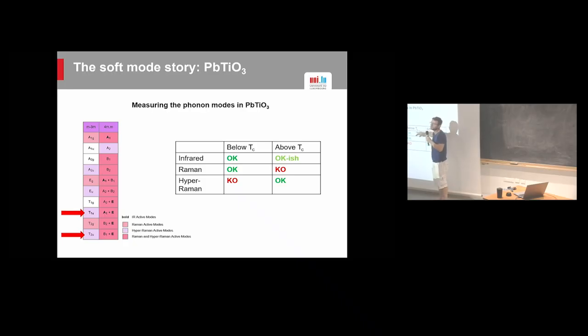Below TC, infrared is perfectly fine. Raman works too, because like I said, in ferroelectrics very often they are active in both. Hyper-Raman doesn't. It's not for symmetry reasons, but it's just that as soon as it's ferroelectric, you're blind because you have so much second harmonic generation that you cannot measure this very small shift, okay?